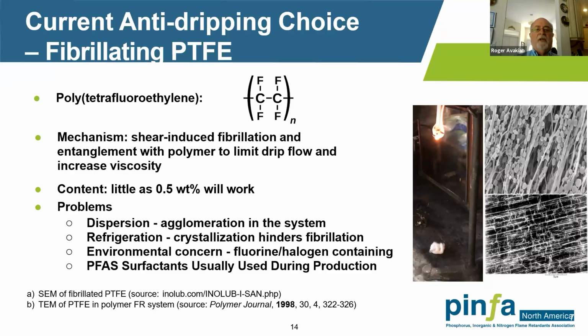But I know, particularly in polycarbonate formulations, typically 0.5% works very well in passing UL 94 V0 in a polycarbonate system at 1/8 of an inch. Obviously, there have been some technical problems in the past, and a lot of these have been dealt with, as we'll see here in a moment. Dispersion: many times you'd get agglomeration from these materials when they came as straight fibrillated PTFE.